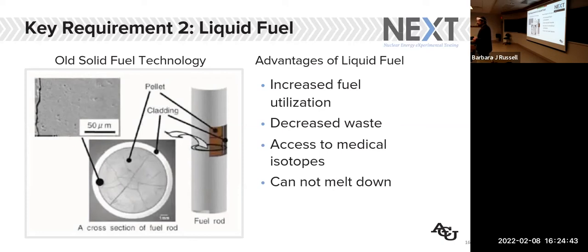This kind of goes into, you might get to it in a couple slides, so you can just wait if you will, but it goes with the reactor lifetime and also the salt question. What are you using for the pressure vessel? Because I know there were some experiments done that showed the lifetime of some metals around salts was pretty detrimental. Yeah, so materials is going to be a huge issue. We're going to use stainless steel 316 because we can get our hands on it and it's an approved material. The NRC understands what it's capable of doing and what its operating conditions are.